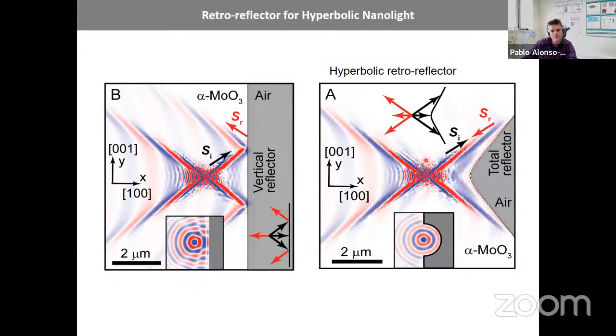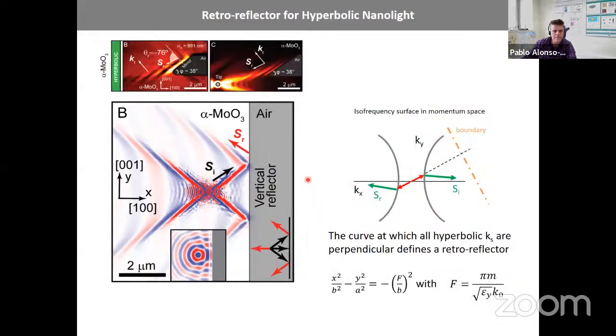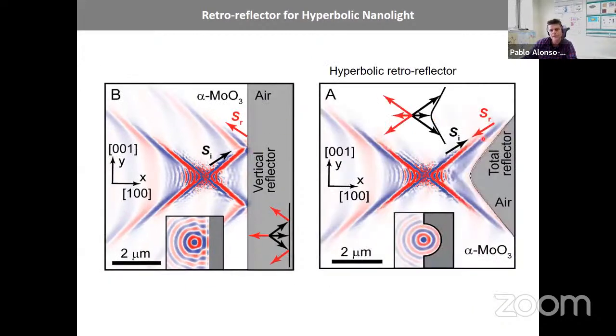We fabricated it, or well, we simulated it first. It has this shape for this wavelength, and this is a numerical simulation. And then here we have the dipole that launches all the hyperbolic waves. And here you can see that as a difference to here, where there are surface polaritons that leave the reflection at the boundary, they outgo at very different directions. Now they all come back to the same point. So we have a retroreflector. All the waves that come back in this hyperbolic wall to this shape, they come back to the origin.